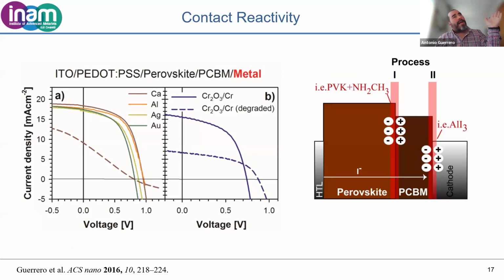And as I mentioned, once the ions get to the contacts, then these ions can also do other things like diffusing through the extraction layers, but also they can give rise to chemical reactions with the contacts. And this is one example that we published already in 2016. So basically, we were characterizing inverted solar cells with different metals. And when the device was fresh, it was giving a good IV curve. And as soon as we illuminated the devices for about 15 minutes, we could see how the devices were degrading very fast. And the shape of this curve could be partly mitigated if we place some protective layers between the metals and the electron transport layer.